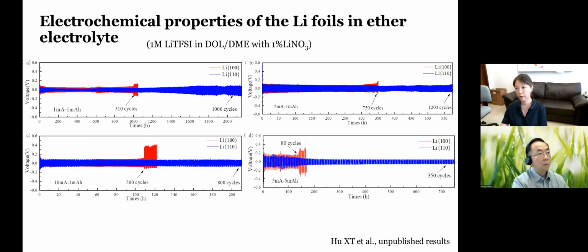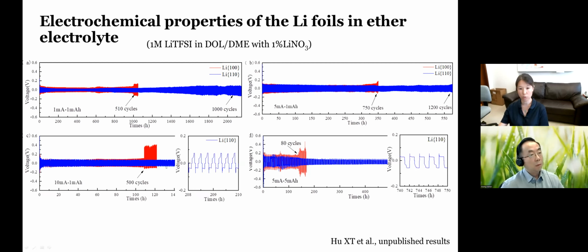Right, and we have also been asked a question. The other results I showed are in the carbonate electrolyte. So does it work also for other electrolytes? It does, right? So we tried ether, and it actually works a lot better in ether electrolyte for obvious reasons. We have these symmetrical cells performed at low current density, low capacity, and mid and high current density, low capacity, and also high current density, high capacity, right? In any of the cases, you see very good performance associated with the lithium 110, right? Much superior to that of the 100, right? So these are the cycles enlarged towards the end of the cycles, right?